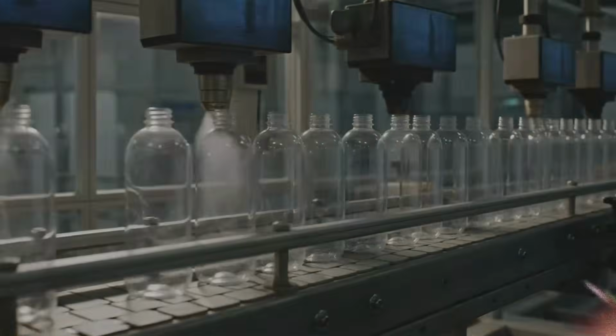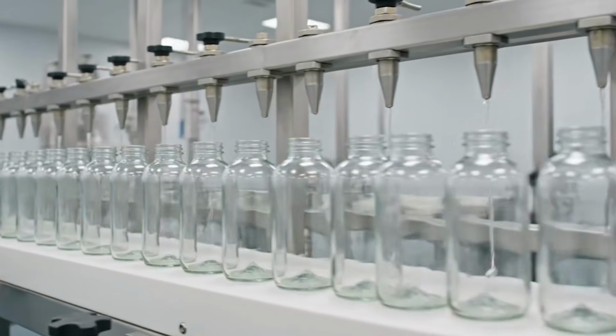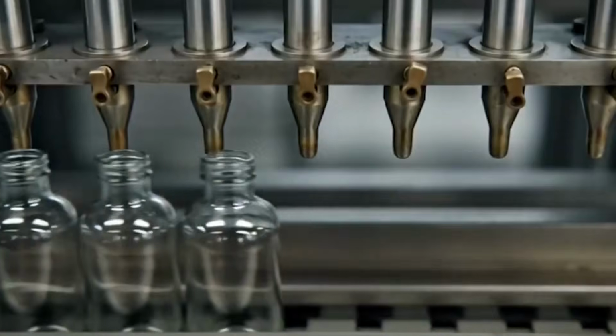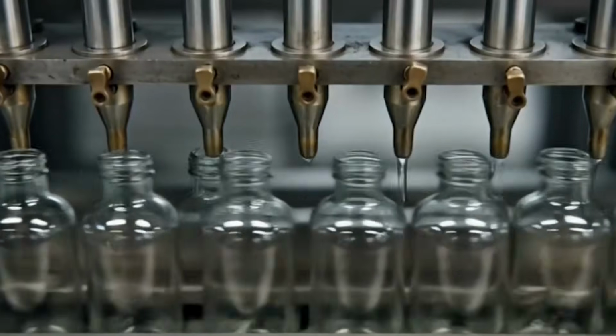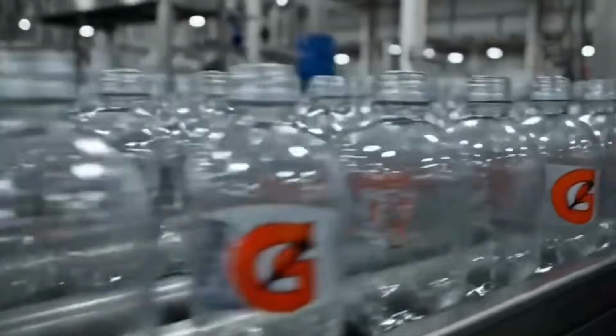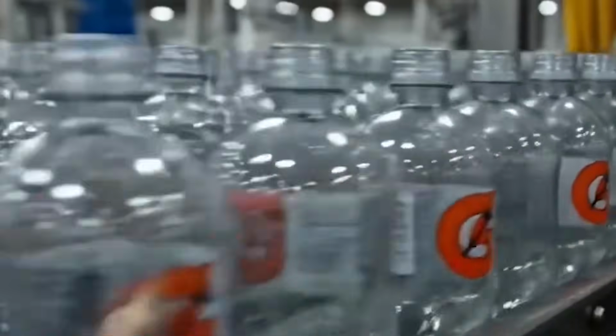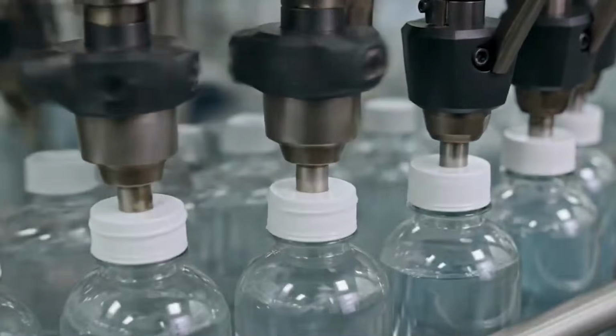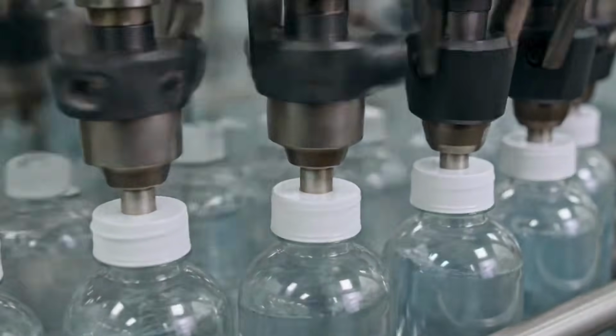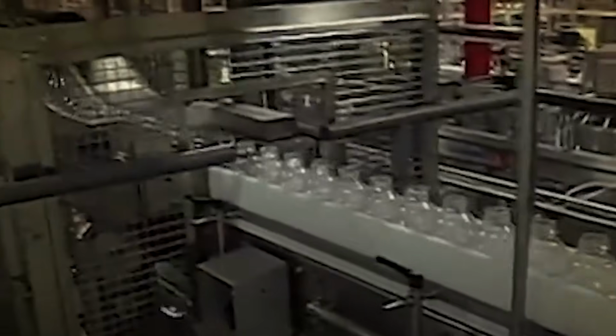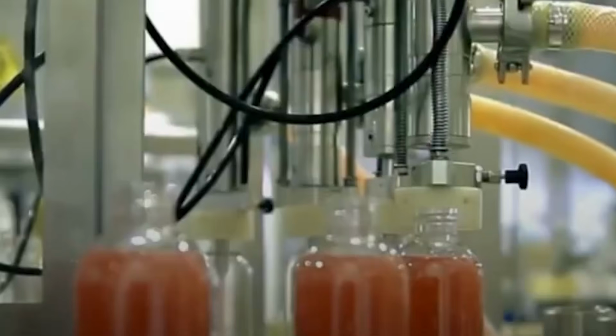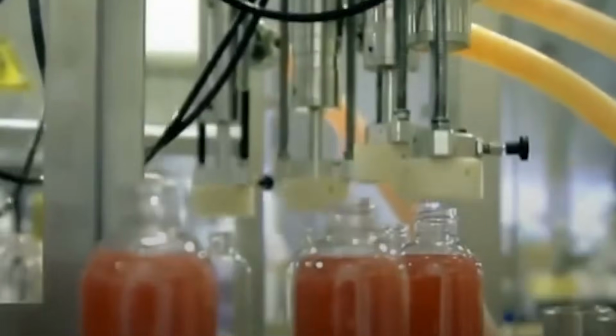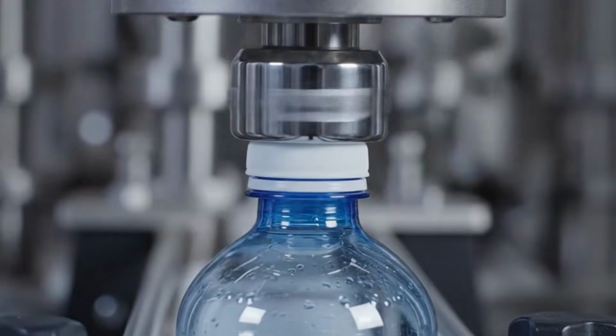The heated preform enters a blow molding station. A metal mold closes around it, carrying the exact outline of the final Gatorade bottle, including its shoulder profile, label area, grip details, and stable base. A stretch rod extends down through the softened preform. It pulls the plastic lengthwise. High-pressure air then expands the plastic outward until it presses firmly against the mold interior. The compact preform becomes a full-size bottle in less than a second.